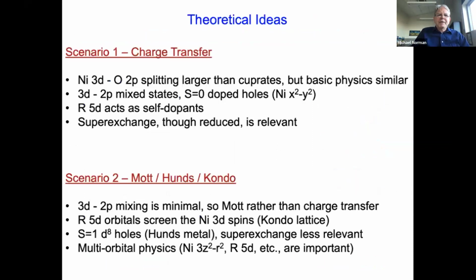So theoretical ideas have sort of been in two camps. One is, yep, the charge transfer energy is larger in these nickelates than in cuprates, but the basic physics is somewhat similar. You get 3d-2p mixed states. The doped holes tend to be spin zero. They tend to reside in the x squared minus y squared orbitals. The effect of the rare earth 5d's is basically to act as self-dopants. You get superexchange, but it's reduced relative to what you see in cuprates, but it's relevant.